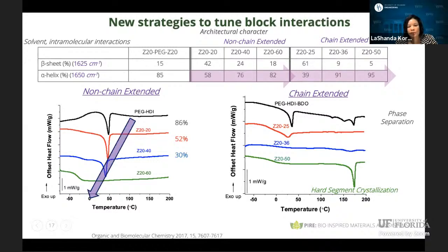By the time you see the Z20-60, you have pure phase mixing between that of the PEG and the lysine structure in these systems. So you have a confinement of soft interactions. And this is facilitated by the fact that PEG and the lysine can form similar helical conformations of a 7-2 helix, and in that way they can actually organize together. For the chain extended systems, a very different picture emerges here.